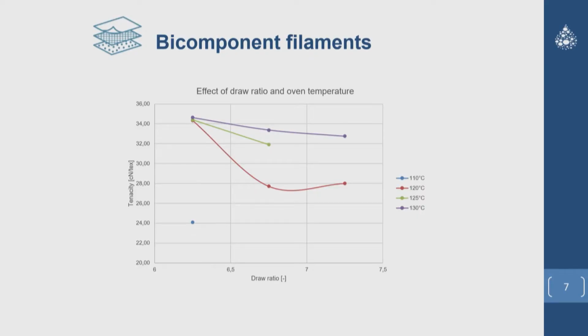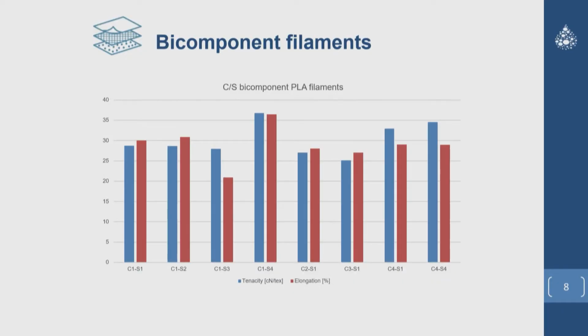During the extrusion, you saw we have ovens, we have a water bath, we have rolls. So we can change lots of parameters. Here you can see what happens if we change the oven temperature, we change the draw ratio, but you can also change the air velocity in the ovens, the water bath temperature. We did this with our PLA, and we did it with lots of different PLA grades. I'm just going to go to the next slide. Here you see all the different core sheath combinations, and we optimize them to get the best results.